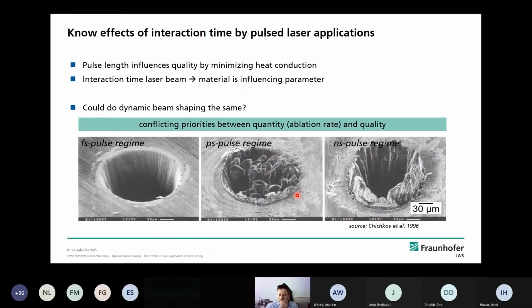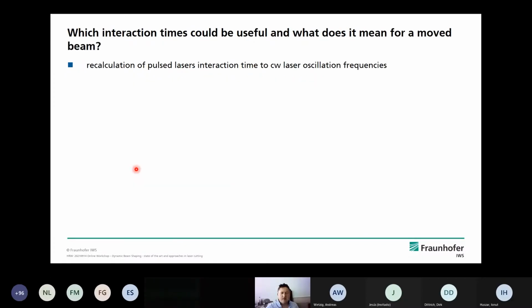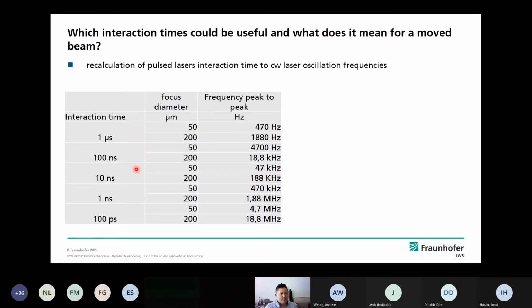My view is, if we look at pulsed laser applications, we know that if we reduce the pulse length, or the interaction time between material and laser beam, we can increase the quality. Of course, I know the important point is not only the laser pulse, it's also the long break between the pulses, but it should give you an impression that we can influence the process by reducing the interaction time and increasing the number of repetitions. So I tried to calculate what's possible.